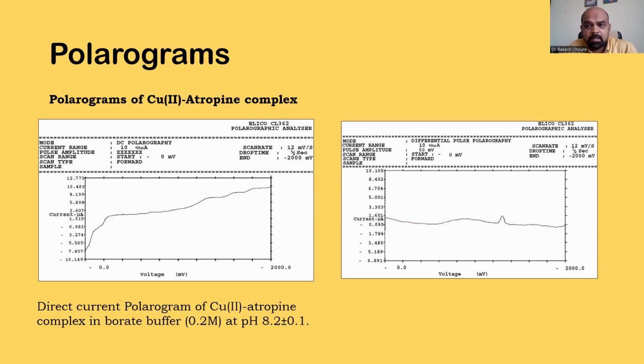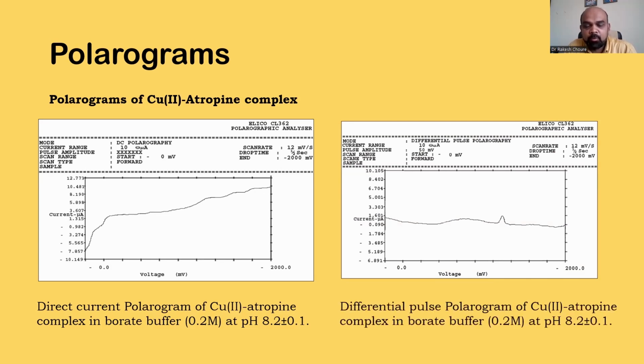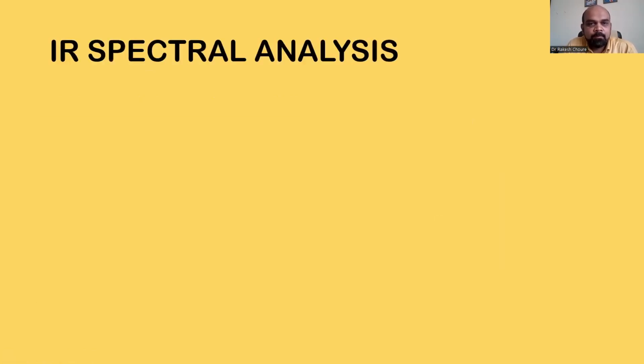So this is the polarogram of DPP, that means the differential pulse polarogram of copper atropine complex in borate buffer solution, that is the supporting electrolyte, at the same pH 8.2. And here you can see the peak. It is the peak of the complex. It has been shifted towards the electronegative potential. It shows that the drug has been modified, it means the complex has been formed. So this polarography data shows the characterization of the modification of that particular drug in the form of a complex.